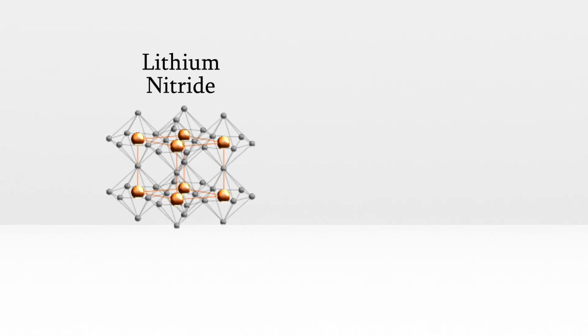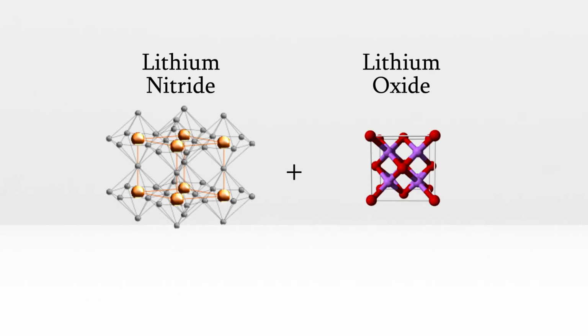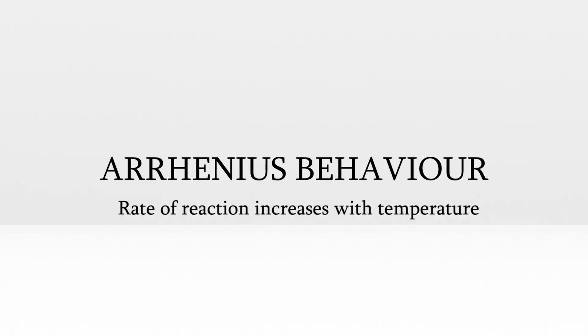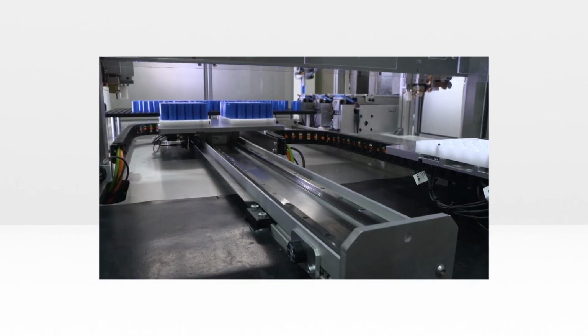By applying these methods to other crystals containing lithium, many hope to create a commercially available solid-state electrolyte, such as lithium nitride, which, when doped with lithium oxide, sees a definite increase in ionic conductivity whilst retaining a high electrical resistance. These cells have the added benefit of exhibiting Arrhenius behavior, which means that ions travel faster through the electrolyte as temperature increases. This is by no means the only way of achieving a solid-state electrolyte.